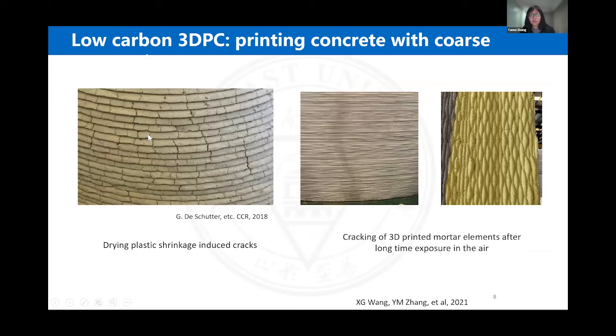That means for the mortar, in 1 cubic meter of mortar, more and more cement will be used for printing. Okay, that means more cement used means a very high carbon footprint for this special material. And another issue is the cracking problem with mortar, because there is no coarse aggregate to restrict the shrinkage of mortar like conventional concrete, which uses many coarse aggregates.